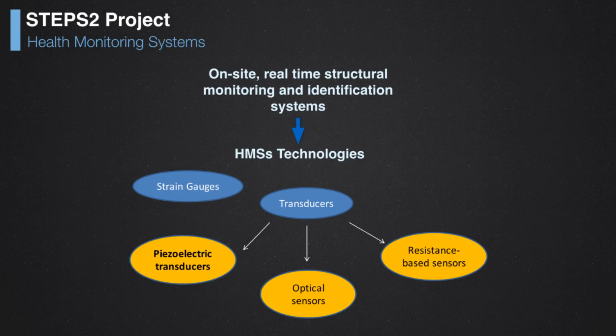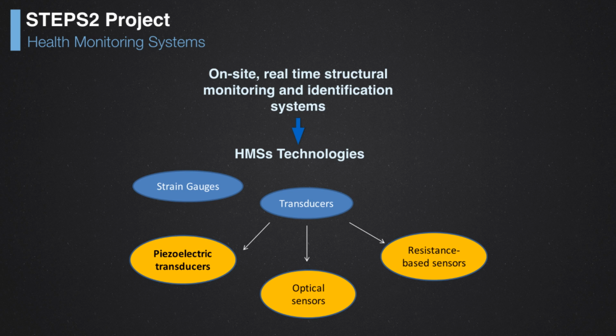Another approach is that of other transducers, like for example the piezoelectric transducers. So in this case you use a material which has a property called piezoelectricity, meaning that depending on the mechanical stress applied, you are able to generate a voltage displacement, charge displacement on the surfaces of such material. We will see more in detail later what this means. Another possibility is to use optical sensors, like the fibers. So you have a laser beam which is injected into a fiber, and the minimal variation of the length of the fiber, when this device contains a grating, produces a variation in the reflectance, the back reflected light. So you are able to simultaneously inject a signal and read out the deformation status of the fiber.